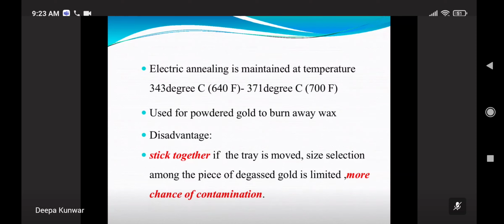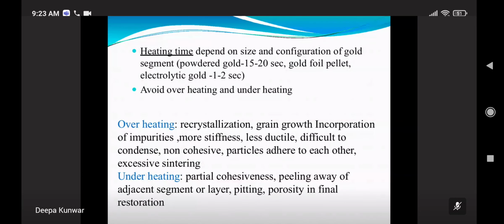Used for powdered gold to burn away wax. Disadvantage is they stick together if the tray is moved. Selection among the pieces of degassed gold is limited. Heating time of the gold segment: powder 15 to 20 seconds and electrolytic gold 1 to 2 seconds.